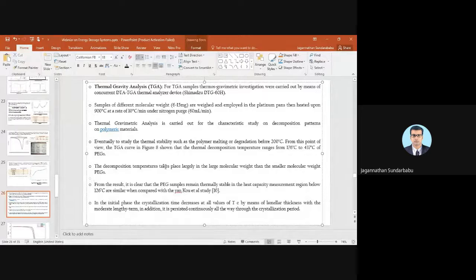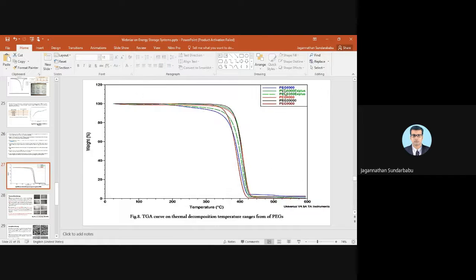So the decomposition takes place at higher temperatures for the larger molecular weights than for the smaller molecular weights, right? From this TGA, it has been shown that the PEG samples remain thermally stable in the heat capacity measurement region, below 120 degrees Celsius or similar, right? So it is stable below 120 degrees Celsius. This is the thermal gravimetric analysis decomposition curve, where you can see that at about 397 degrees Celsius the temperature drops, right? So this has been characterized for different PEGs, right?